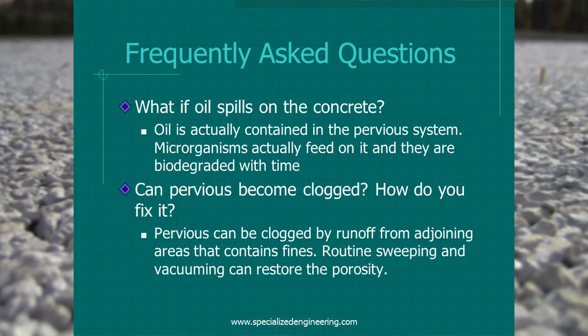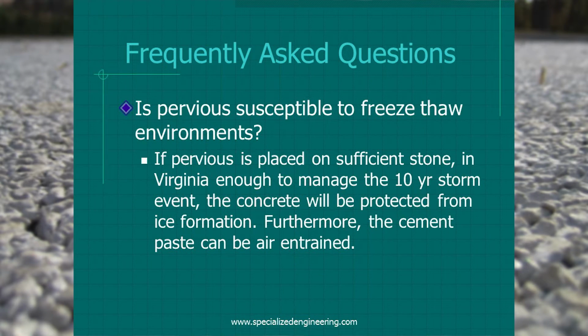Pervious concrete can become clogged. It gets clogged typically where you've got runoff from adjacent facilities, whether it's other pavements or grass areas. Soil will run off. It can also be from the concrete itself, from the raveling process. And that's why routine sweeping, which we'll talk about, and vacuuming can restore it. In freeze-thaw environments, if it's designed properly and that water is designed to stay in the gravel layer below and you don't have clogging on the surface, it's very resistant to freeze-thaw.